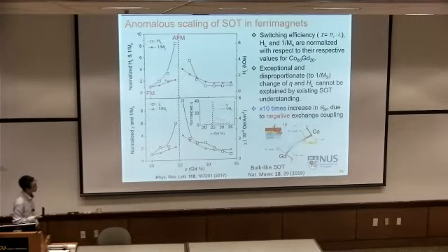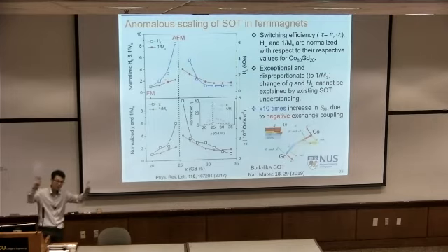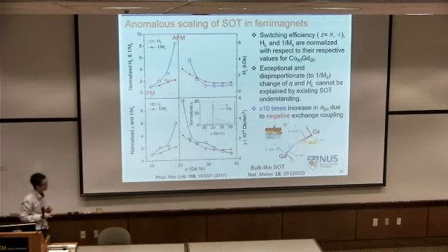We attribute this to a negative exchange coupling between cobalt and gadolinium. If we give a torque to the cobalt lattice, gadolinium should follow to help maintain the antiparallel configuration. This is quite different from a conventional ferromagnet, where everything points in the same direction.